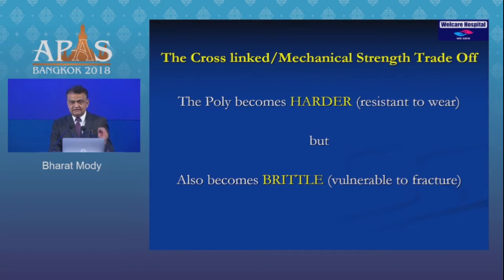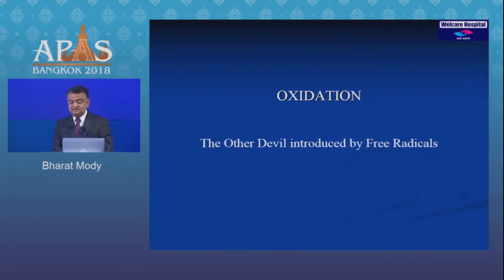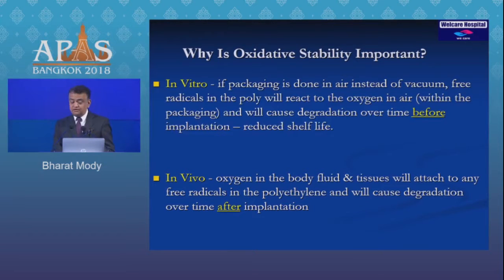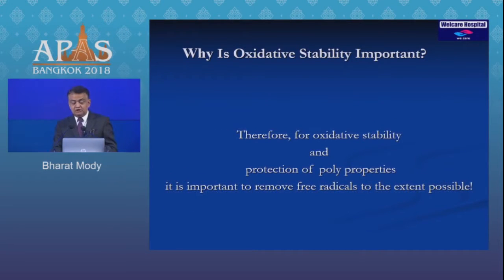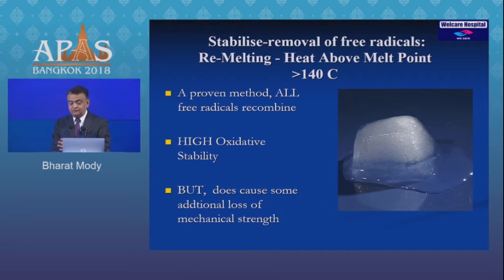In other words, this is the one-line message. The poly becomes harder and therefore resistant to wear when you increase the cross-linking, but it also becomes brittle and therefore vulnerable to fracture as the wear resistance increases. The other devil introduced by free radicals is oxidation, and this can occur in vitro, in the form of the free radicals reacting with the oxygen present in the air or in the packing, and therefore most of the time it's vacuum packing that is done now, or in vivo. Once you put the poly in the human body, the oxygen within the human tissues and fluids can react with it. So oxidative stability is very important, and therefore this stabilization is achieved by doing thermal processes.